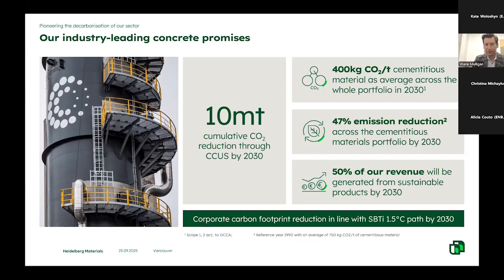Another one is this 400 kilograms of CO2 per ton of cementitious material. That figure probably feels somewhat abstract to many on this call, but the old rule of thumb used to be that 1,000 kilograms of cement meant 1,000 kilograms of carbon. That's changed a little bit with some best practices that have been rolled out globally.